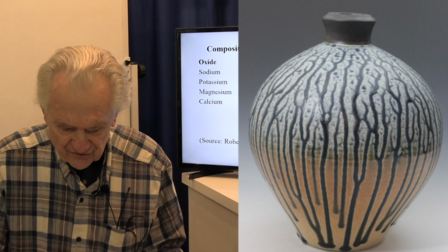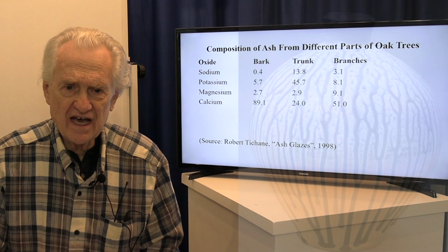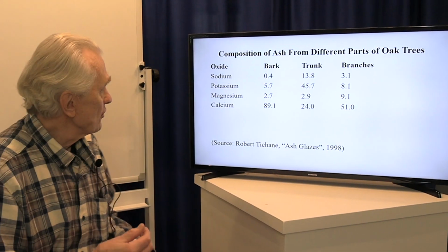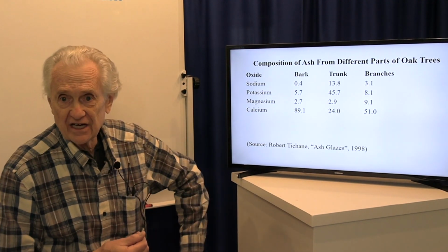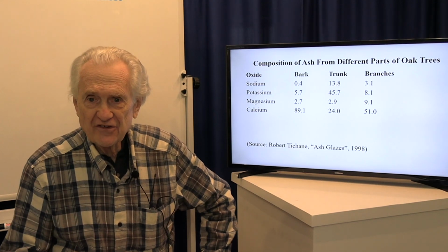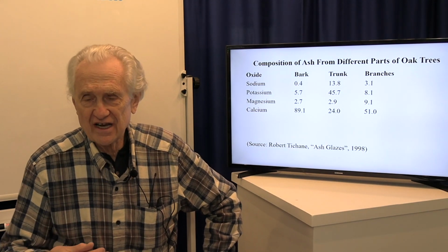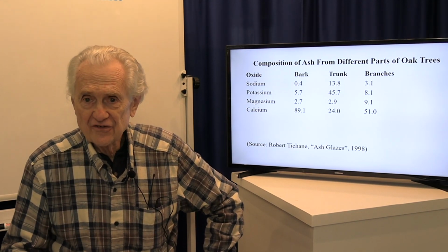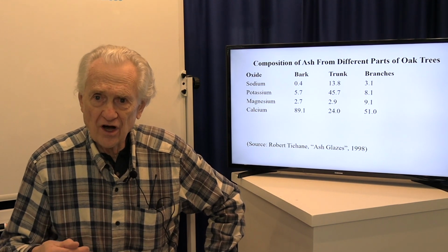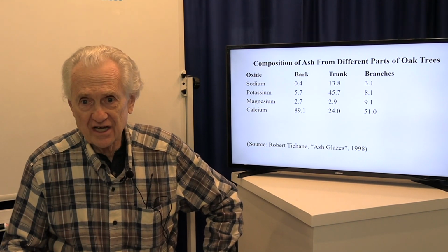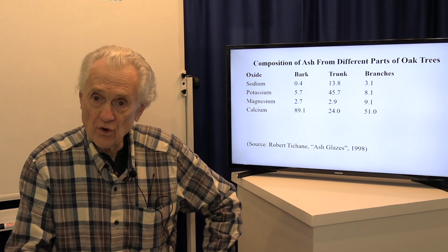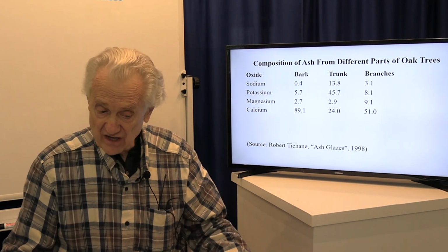One final comment is that when you've washed the ash, you've removed a lot of the sodium and the potassium from the ash. So the ash basically is no longer as concentrated in fluxes as it used to be. So you might have to use more washed ash than you would the same amount of unwashed ash, because you've basically made it less concentrated.